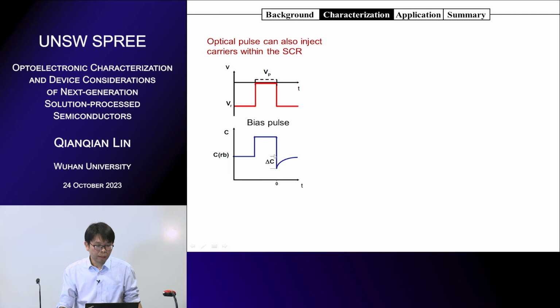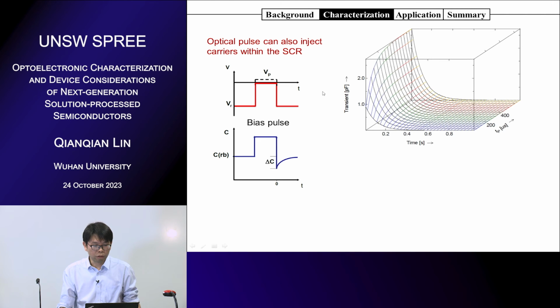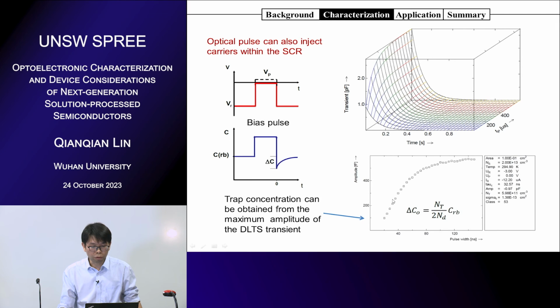So we can inject carriers with forward bias, or you can also use a laser to optically inject carriers or change the space charge region as well. And you can modulate the width of the pulse or the amplitude of the pulse. You will get different transients, and you can get the saturation of the space charge region. So from the saturation, you can get the number of trap states, not the energy level. So here is the number of trap states, the density.